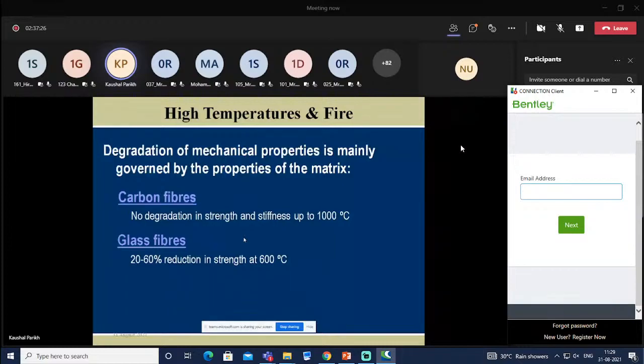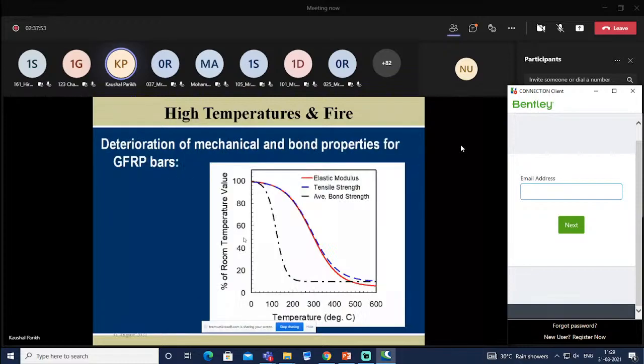As we stated earlier, the matrix is one of the main weaker components as far as fire is concerned, as far as higher temperature is concerned. Glass fibers are susceptible even at lower temperatures, with a reduction in strength of up to 60% at 600 degrees centigrade. So this is one of the typical graphs which shows the temperature versus the percentage of room temperature value.